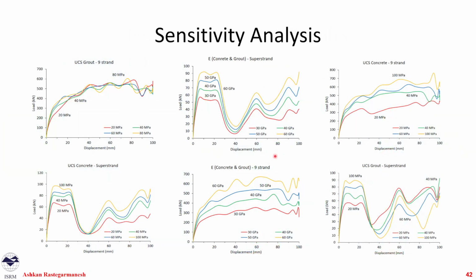Once we calibrated our model to the best of our ability, we did some sensitivity analysis to see what's the effect of changing different things. So we changed the UCS and modulus of elasticity, and we realized that, for example, for our bolt cables like 9S, the change in E of the concrete and grout has a major effect. But for the UCS of the grout and concrete, the grout has little effect, which is interesting because you don't expect that. But for our concrete, it has a high effect.